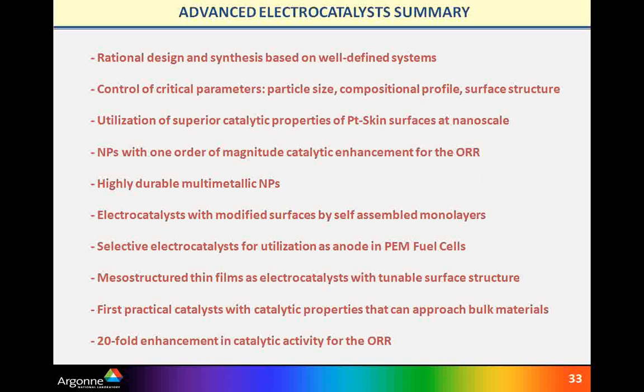So here is the last slide for today, which is a summary of whatever was achieved, and the message to take home would be that our approach and knowledge from single crystals and well-defined systems is really essential, and we are using that as a guideline to perform a systematic approach with corresponding practical catalysts. I purposely said practical catalysts because they can be at nanoscale or mesoscale. They can be nanoparticles or mesostructured thin films. And so far, in practical catalysts, we were able to achieve enhancement in activity as high as 20-fold improvement for the oxygen reduction reaction.